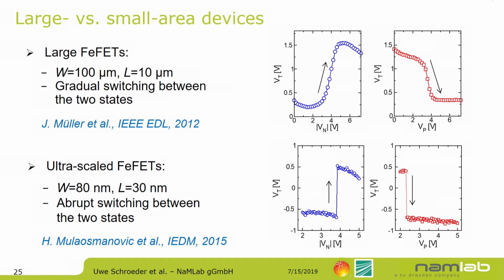But if you now scale your devices to smaller and smaller structures, and here in this case it's a 30 nanometer times 80 nanometer structure, and if you remember the TEM image in the beginning, this is about 1, 2, 3 grains in the transistor structure. We see here very abrupt switching between the two polarization states.